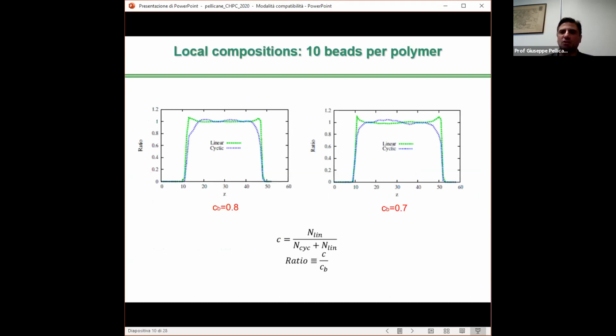So we tried to find the evidence, the smoking gun, in the regime of low cyclic polymer composition, as was suggested by the experiments, and we found it. In these plots, the local composition along the box slices in the Z direction is divided by the bulk composition set up in the box, and shows that for small degrees of polymerization, linear polymers are more adsorbed at the low and high Z surfaces.